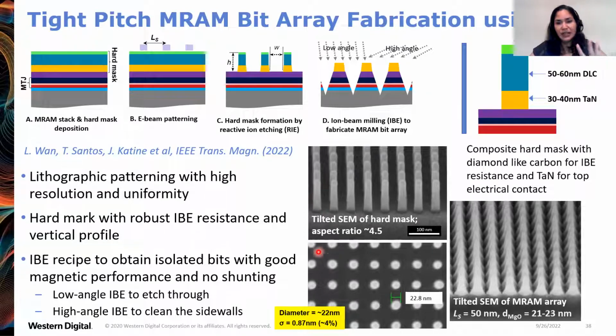This is a tilted SEM. This lower one is the top-down view. And you can see there's a high aspect ratio of the hard mask with very vertical sidewalls. This is what's absolutely critical for a good hard mask. So now, using this hard mask, we're ready to mill into the MRAM stack. We do this by ion beam milling, first at low angle to etch into the depth of the stack, and then at high angle.